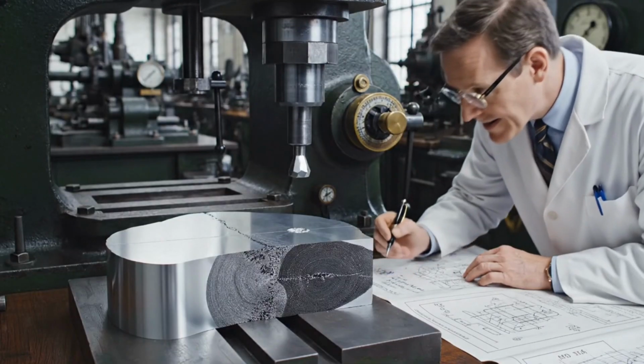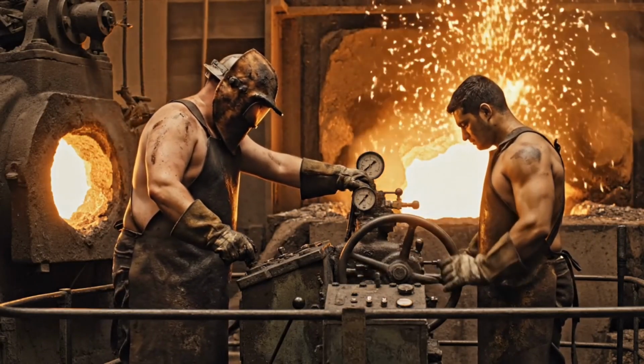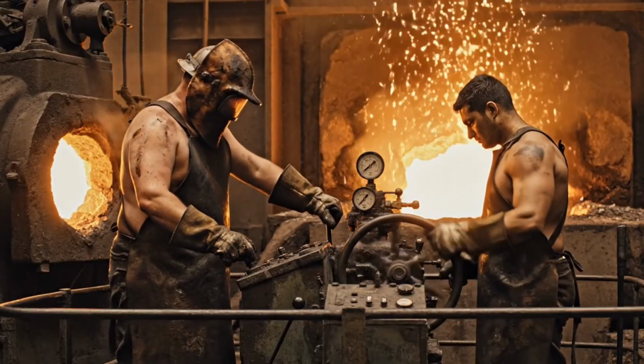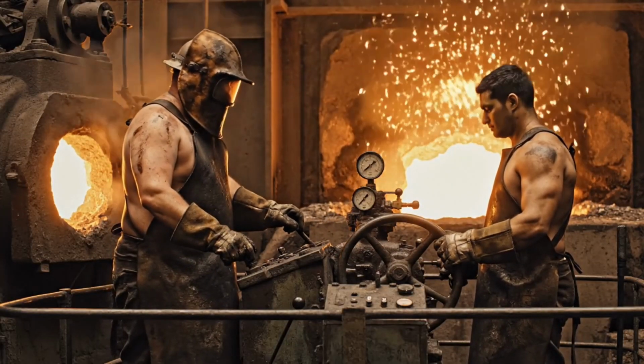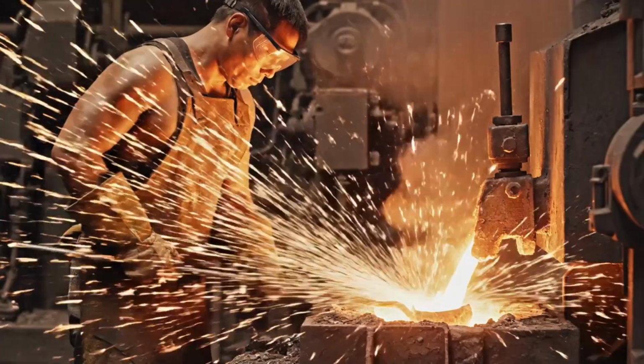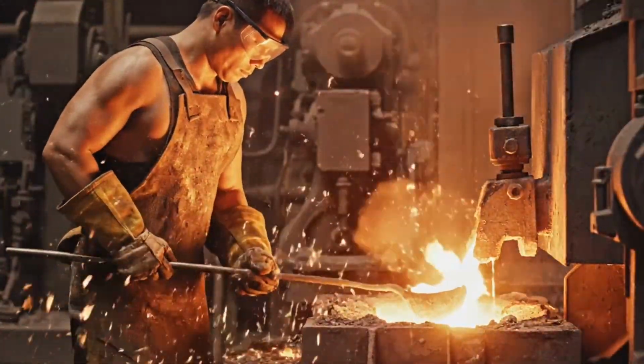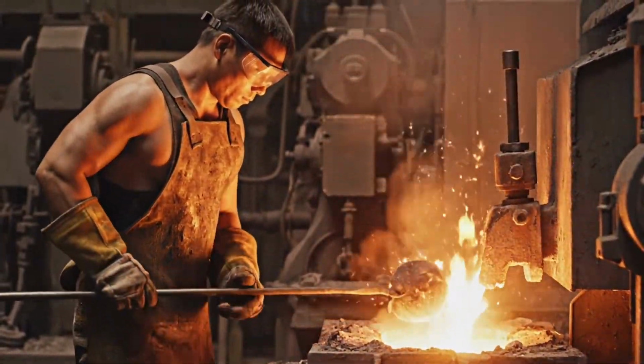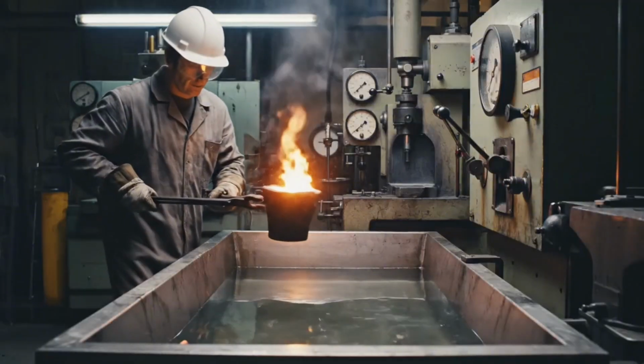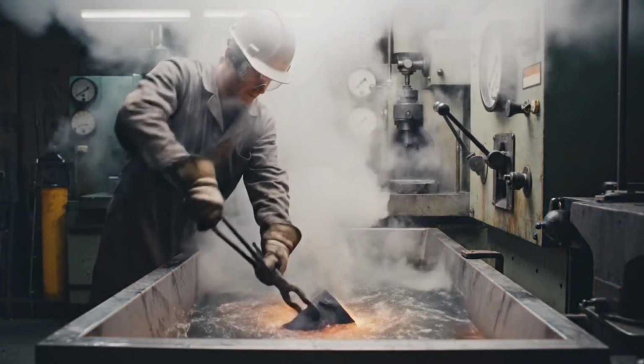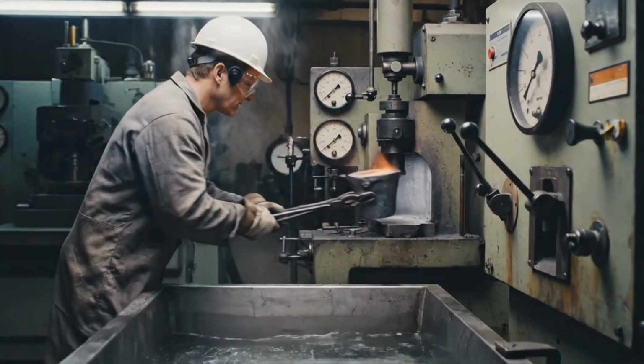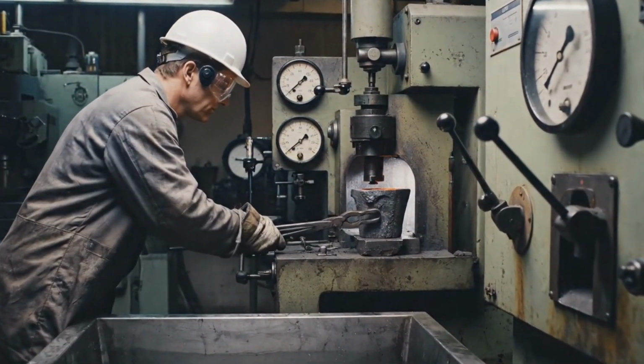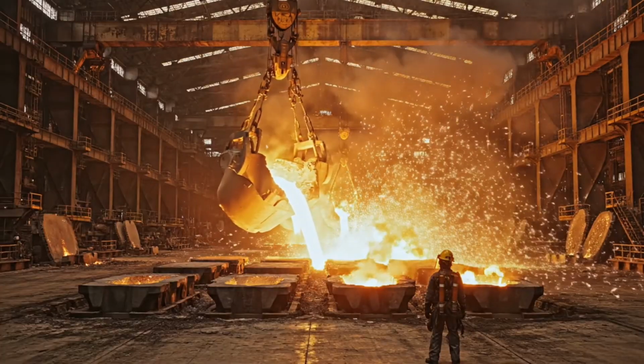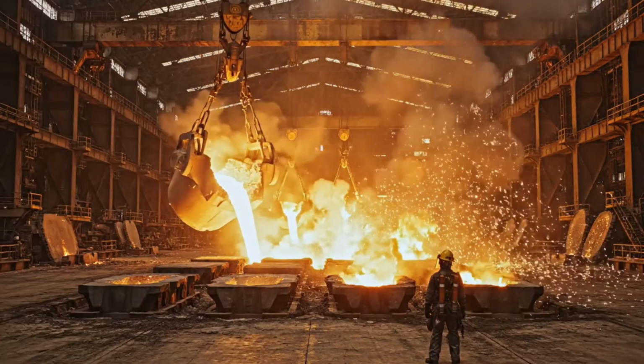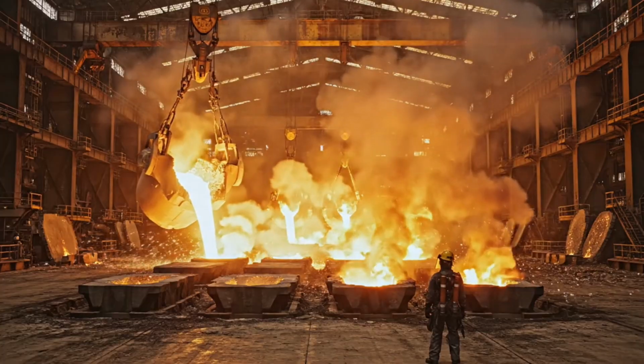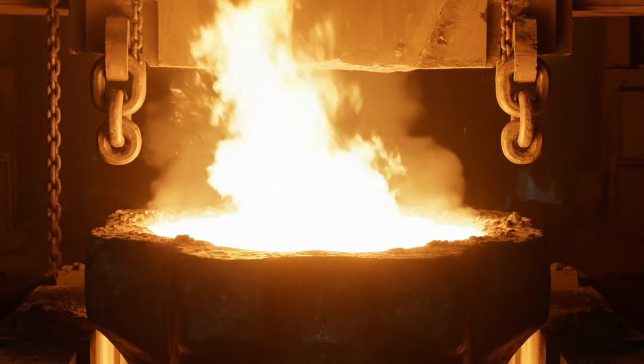These alloying elements would give the final steel its ability to resist penetration, while remaining tough enough not to shatter under impact. Furnace operators, their faces protected by tinted goggles and leather hoods, used long tools to take samples of the molten steel, which were quickly cooled and then tested for carbon content and other properties. When the chemistry was perfect, the steel was poured into massive ingot molds, each one creating a block of steel that weighed several tons and glowed white-hot.